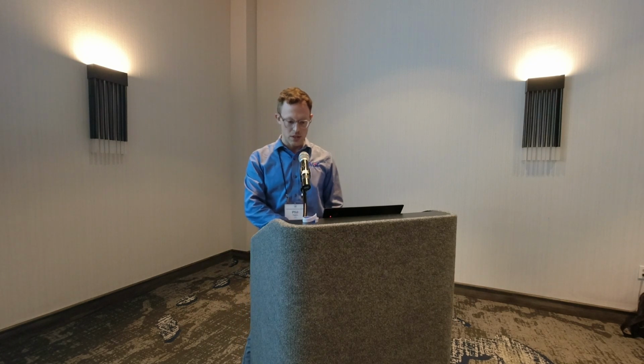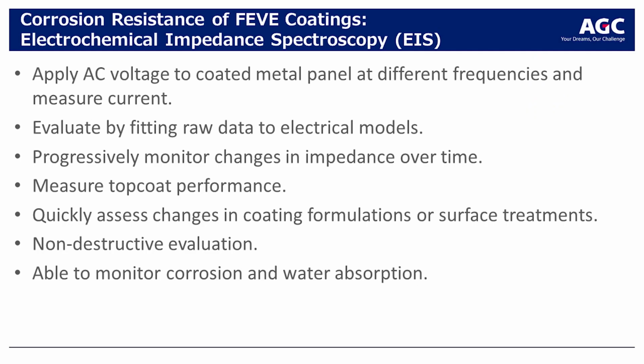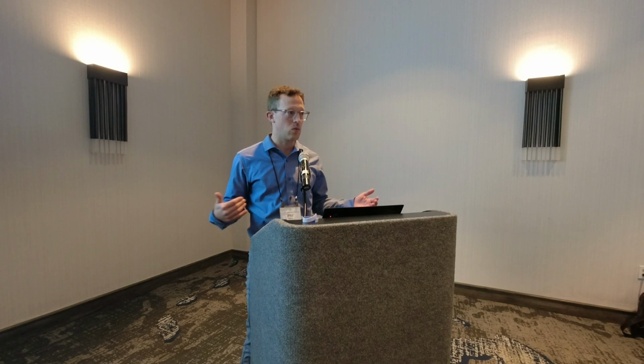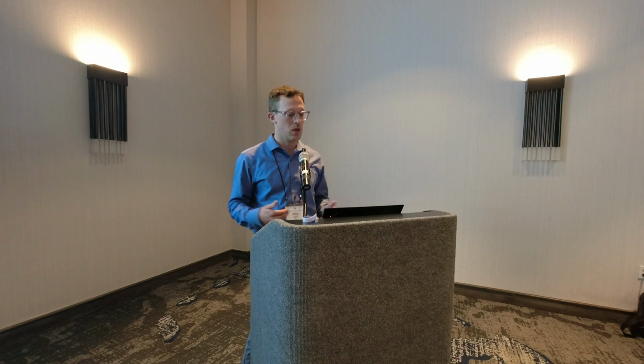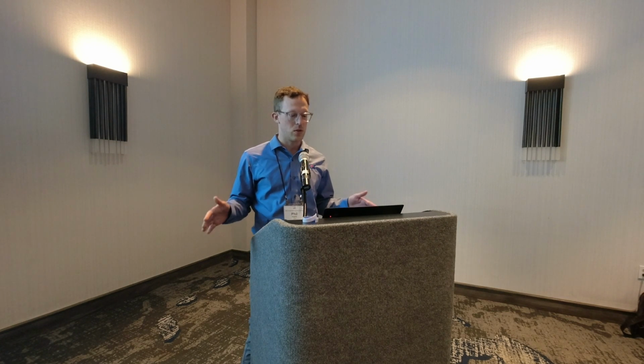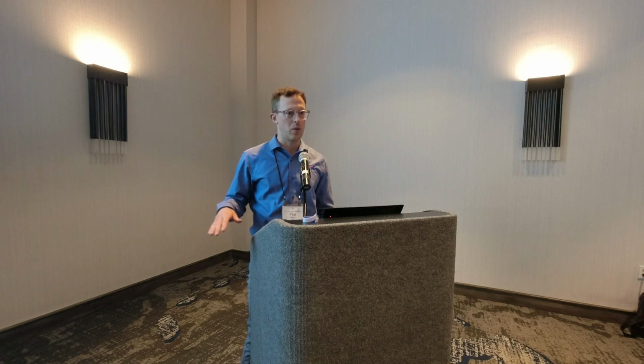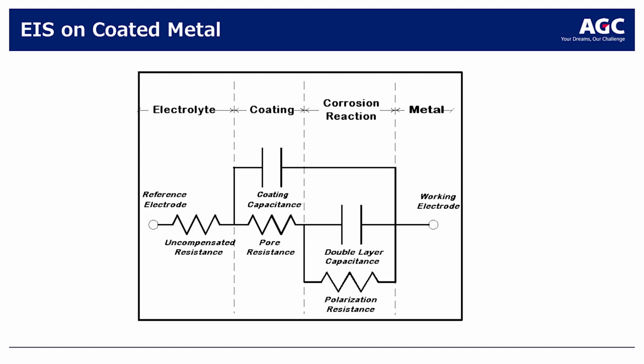And what's pretty cool is that another area that we're looking at is electrochemical impedance spectroscopy. That's one of the aspects that we're pretty excited about, and within this testing, essentially you're going to test your full formulation, and it gives you a way to rapidly test. Of course, we want to age it, because aging is one of the benefits of the Lumiflon system. So what we did was we took this electrolyte, put it on top of the coating, put it on a panel, and we went through and tested it. So we went through all of these surface treatments, non-destructive. We wanted to monitor the corrosion and the water absorption.